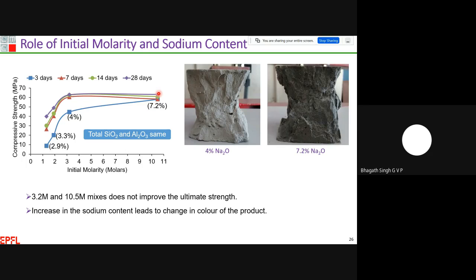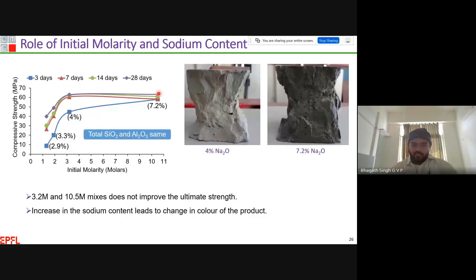But what will the molarity or sodium content do in the system? Increasing the molarity leads to an increase in the sodium content in the activated mixes. With the 4% sodium content, which means about 3.2 molars, you can see the color of one of the failed cube specimens. And with the 7.2% sodium content, this is about 10.5 molars